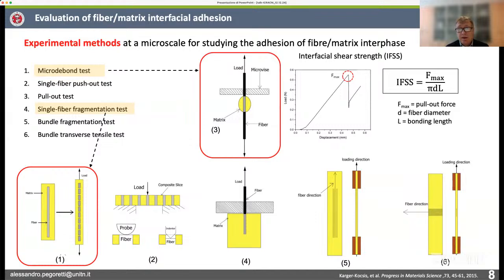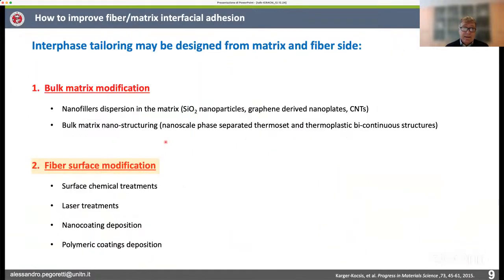In the first case, the load necessary to debond a single fiber from a matrix drop is basically measured. In the second case, in the fragmentation test, we are measuring substantially the length of the fiber when the saturation of the fragmentation process is reached, which is proportional to the critical length, and therefore we can try to find a link between this critical length and the adhesion at the fiber matrix interface.